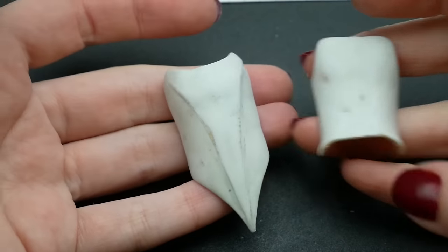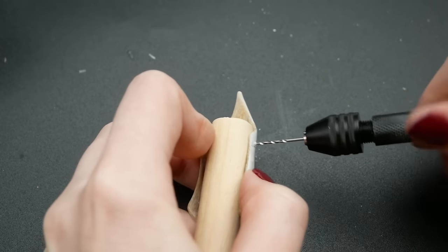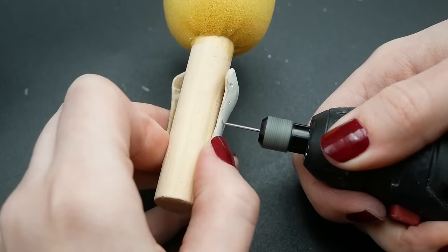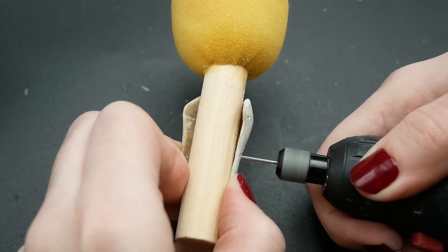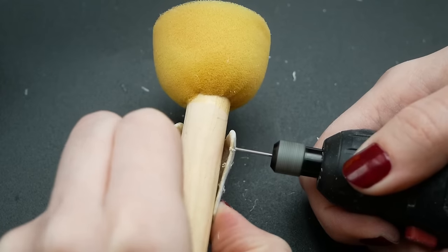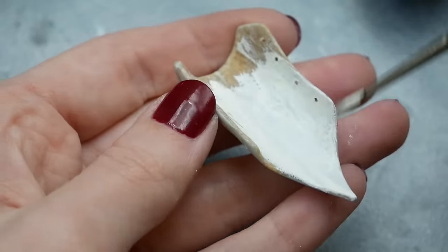When I'm happy with the shape of the armor, I drill holes in it for the future lacing. At first I wanted to use a hand drill because I thought these pieces are fragile, but it wouldn't go through the thermoplastic and I only could drill into epoxy. It's still good though, because now I at least have the pilot holes that will hold the Dremel in place. The power tool goes into it like butter though, because quick rotation warms up the drill and it kinda melts into thermoplastic. I start painting the armor from the inside with enamel paint.